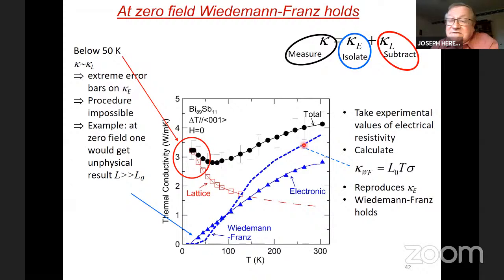Yes, the Lorenz number is probably a little bit lower at zero field at room temperature. And that's probably because the inelastic scattering time for electrons is different from the momentum scattering time. It's a little bit shorter. So that we can reasonably explain.